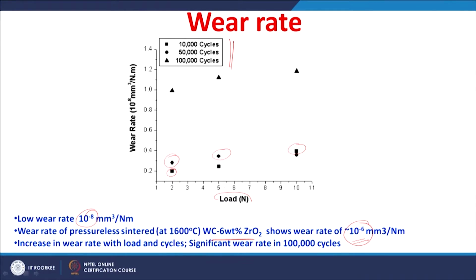But if you look at the 100,000 cycle test, at lower load itself the wear rate was very high, almost one order of magnitude higher than that obtained for the 10,000 cycles test. So, it increases monotonically with the load. The highest wear rate is obtained for the test done at the 10 Newton load for 100,000 cycles. So, this information indicates that the wear rate varies with the load as well as the fretting duration, similar to what we observed for the friction. Friction also changes with the load or the fretting duration.